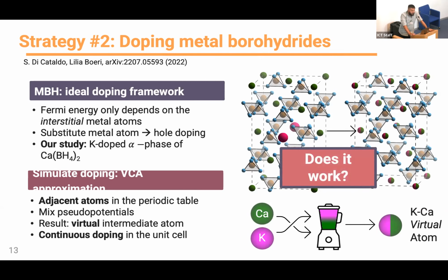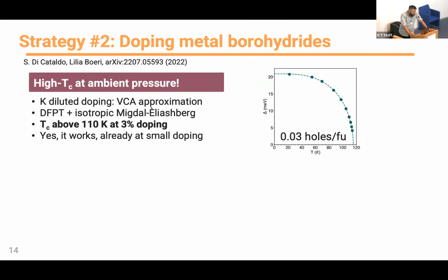So does it work? The answer is yes. You can see in this figure I'm showing the superconducting gap against temperature, and you can see how it closes at TC. This is for a doping of 0.03 holes per formula unit. This was obtained by density functional perturbation theory and then solving the isotropic Migdal-Eliashberg equations.